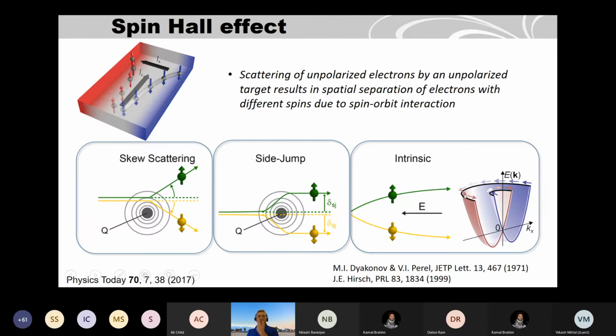And how to understand this? There were many papers before that to explain such behavior. For example, there can be some scattering from the atoms here. If these atoms are very heavy, like platinum, gold, and tantalum, the electron can scatter. This is called skew scattering if it happens on one side, and it's called side jump if it happens on both sides. So these are scattering mechanisms, and there is also an intrinsic effect, the intrinsic spin Hall effect, which comes from the band structure of the material. Let's say you have a Rashba type of band structure, so the band is split due to spin orbit coupling. When you apply an electric field here, you get a spin polarization. So this can be due to spin orbit interaction in your material.